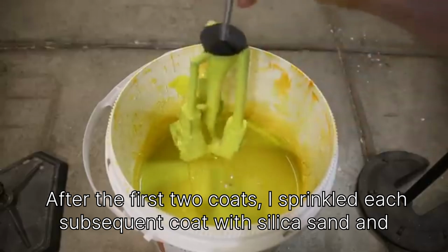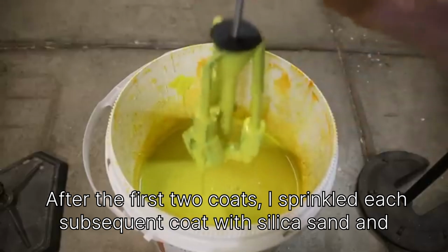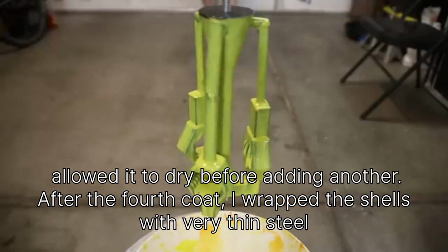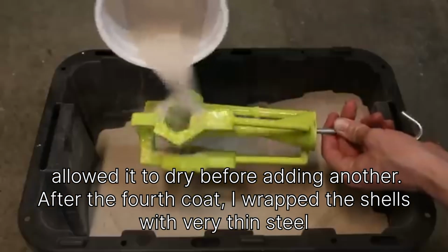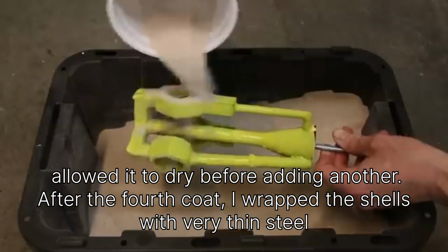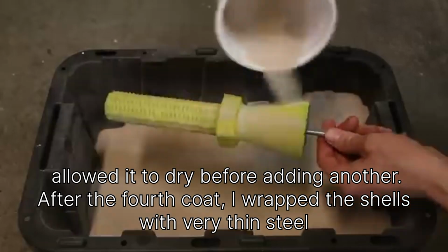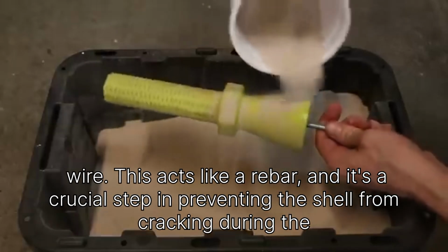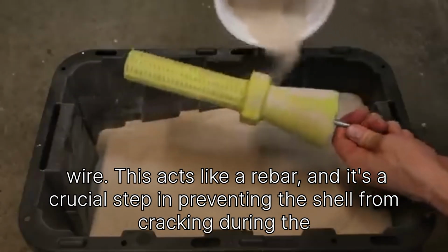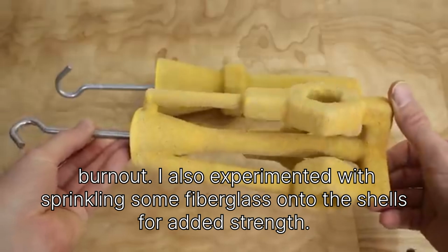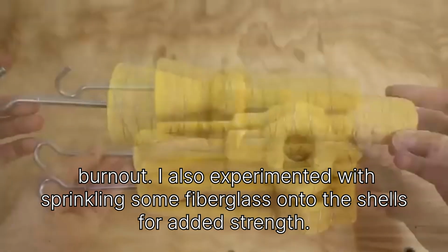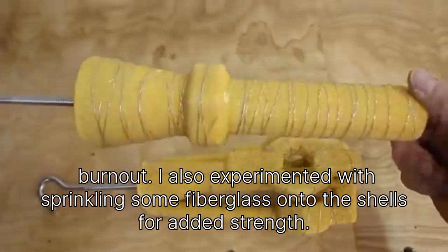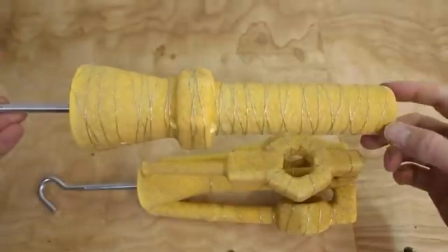After the first 2 coats, I sprinkled each subsequent coat with silica sand and allowed it to dry before adding another. After the 4th coat, I wrapped the shells with very thin steel wire. This acts like rebar, and it's a crucial step in preventing the shell from cracking during the burnout. I also experimented with sprinkling some fiberglass onto the shells for added strength.